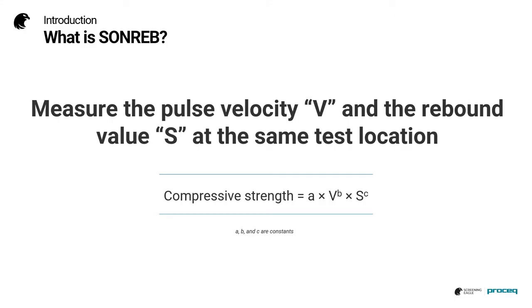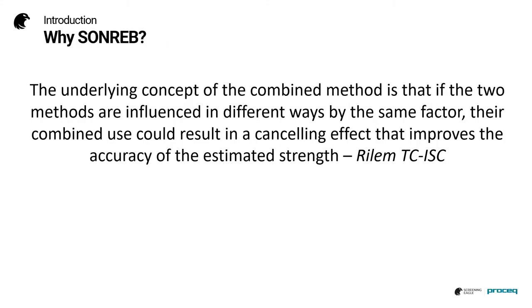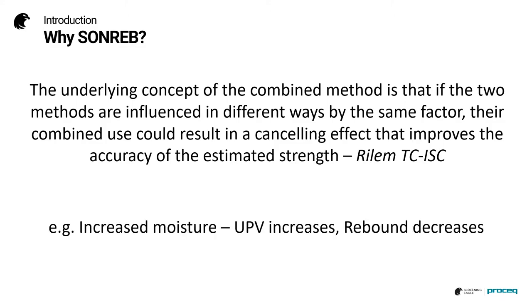In simple terms, we measure the pulse velocity and the rebound value at the same test location, and then we obtain a compressive strength estimate based on an equation of the format shown here. The underlying concept of the combined method is that if the two methods are influenced in different ways by the same factor, their combined use could result in a cancelling effect that improves the accuracy of the estimated strength. For example, if we have increased moisture content, the ultrasonic pulse velocity value increases, whereas the rebound value decreases.